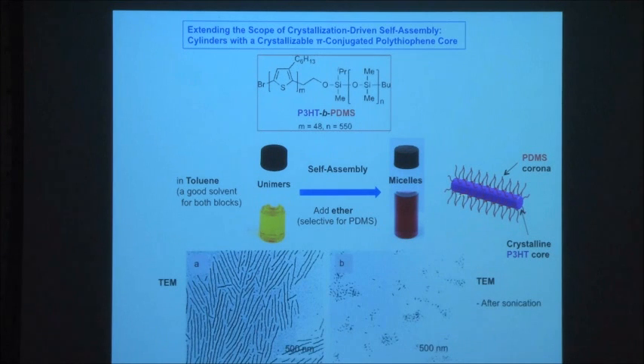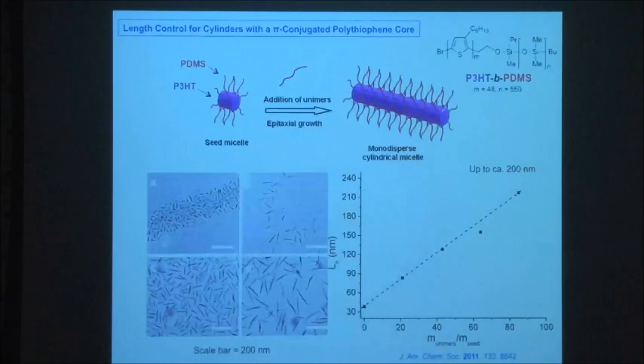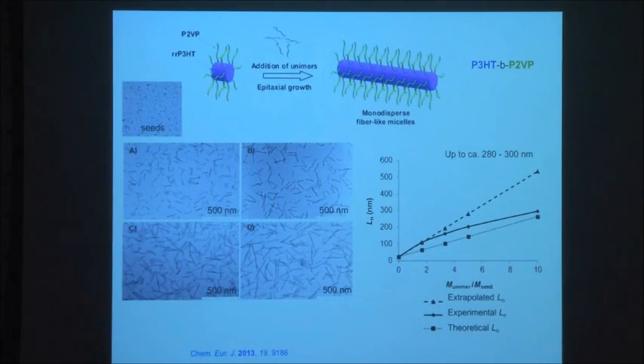And you can show by electron microscopy you have these fiber-like cylindrical structures, and you can sonicate these down to give seeds. And then you can think about growing the structures. If you add block copolymer unimers to the seeds, they will grow, and they do grow. But there's a problem, and that is they grow up to about 200 nanometers and then stop growing. A problem here, we think, is the fact that the poly-3-hexylthiophene crystallizes so fast you introduce defects into the core, and eventually it will no longer grow because there are just so many defects in the core of the micelle. And we've been exploring ways to get around this.